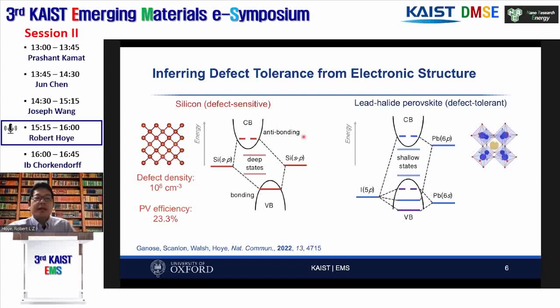And that's certainly the case with traditional semiconductors like silicon, where you need to manufacture these with defect densities down to a very low value of about 10 to the 6 per centimeter cubed. And this is necessary in order for these to work in electronic devices, such as in these polycrystalline solar cells here. But with the lead halide perovskites, we have millions of times more defects than what you'll find in silicon. And yet in polycrystalline solar cells, you already can achieve a higher efficiency.